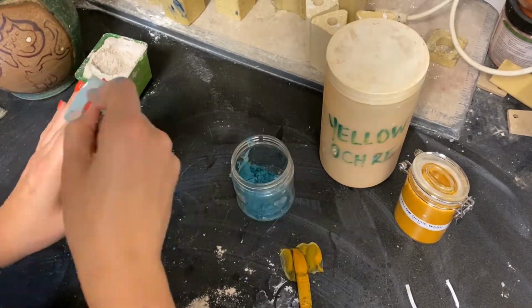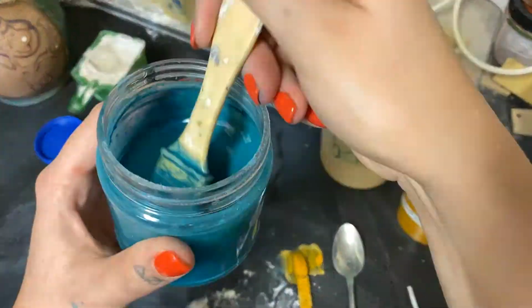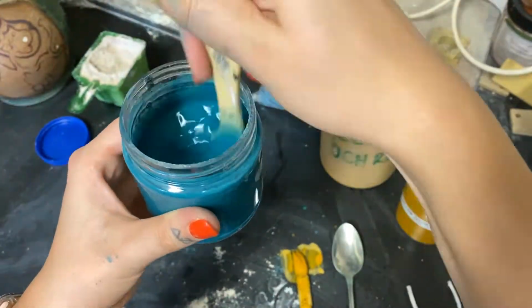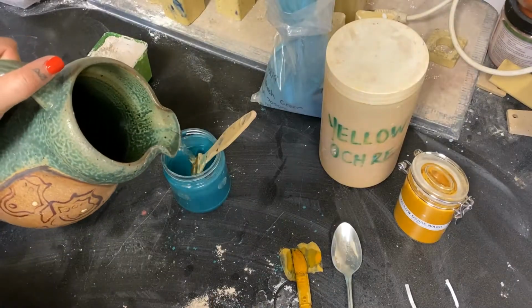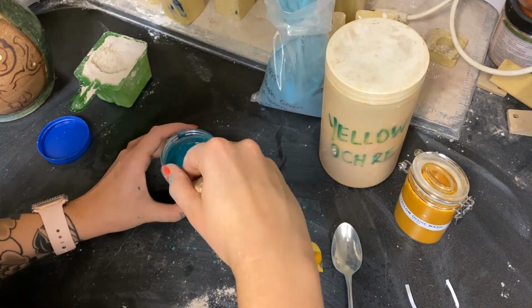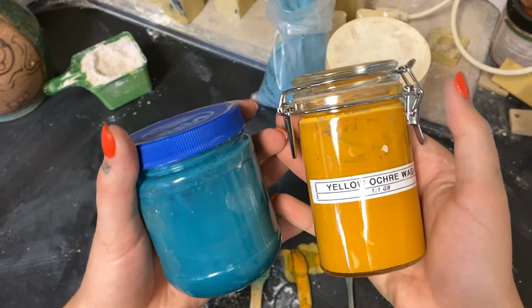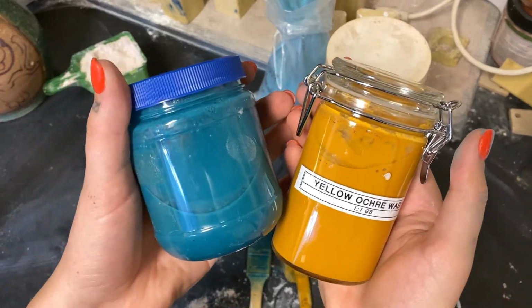For mason stains, I'll use a 1:3 or 4 ratio of Gerstley to stain. So, 12-ish scoops of stain to 3 scoops of Gerstley Borate. Make sure to always stir, not shake your wash bottles. This gets particles off the walls and prevents a lot of bubbles.